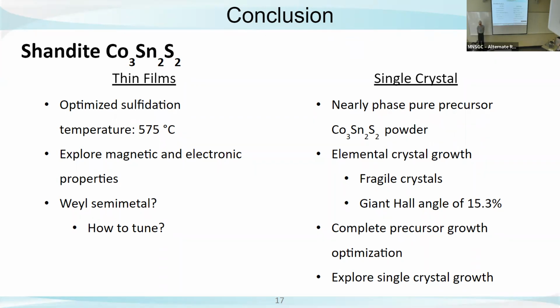Yeah, go ahead. So you mentioned that this material, this shandite, has this anomalous Hall effect. Is that based really on that one previous measurement? Because you also said that it was really hard to actually make. So you've got one previous measurement by some other group observing this, and then your work, or was it theory that predicted the anomalous Hall effect? Yeah, it's just the one measurement that we saw in the previous literature that we started this material from. There was previous research done on it being a Weyl semimetal, but no one to really back that until that paper.